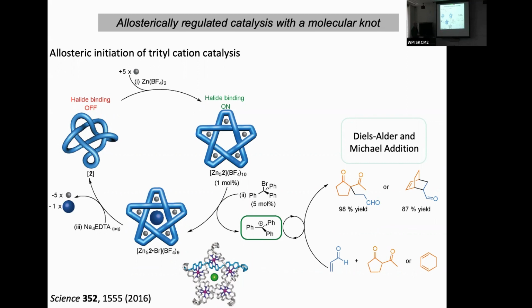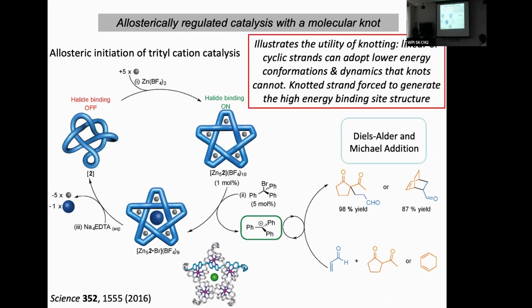So if we treat that with an alkyl halide, such as this trityl bromide, the knot here will strip the bromide off this molecule to form the trityl cation, and that trityl cation can be used to do chemistry. So for example, it can be used as a catalyst to promote Diels-Alder reactions and Michael addition reactions. So this knot can actually produce the catalyst for this chemical reaction. Once the bromide is in the center here, we can then remove the metal ions again with sodium EDTA and reform the knot. So this is an example of allosteric binding. So the binding of the metal ions by the knot creates another binding cavity for something else. And it's sort of an example of what knotting can actually do.